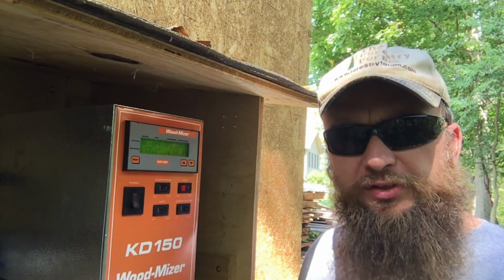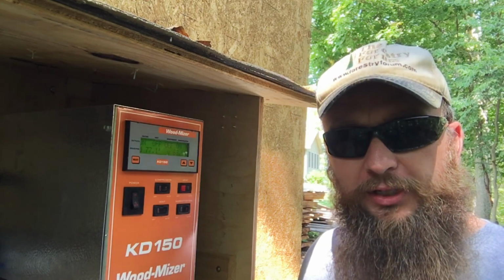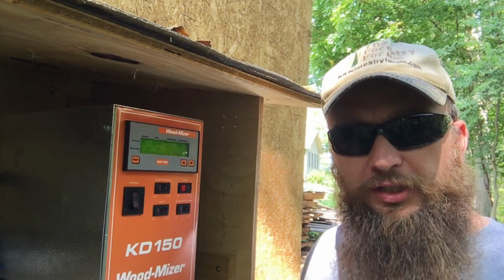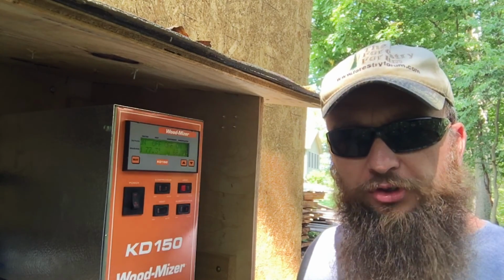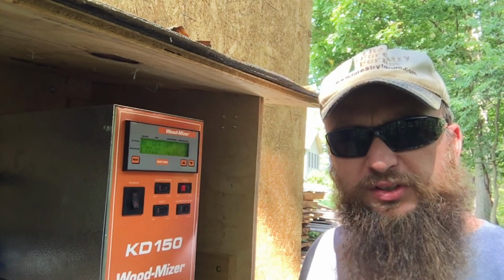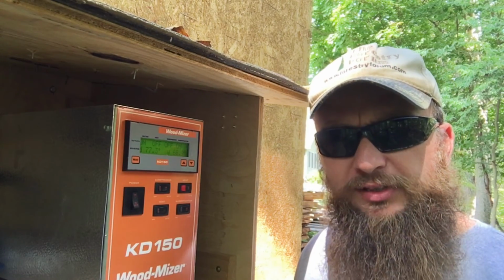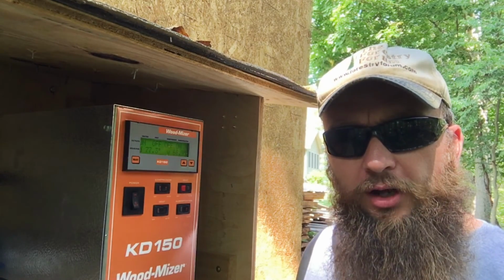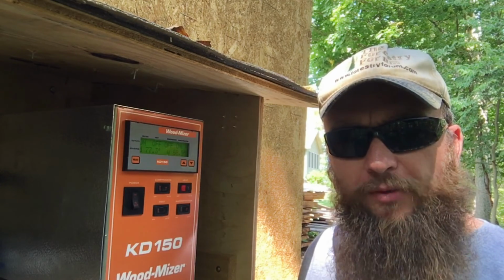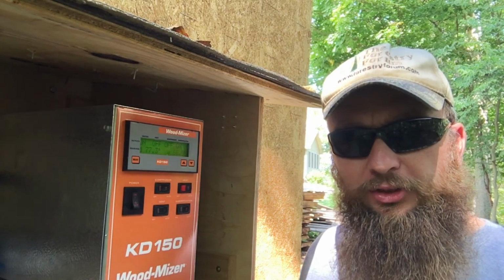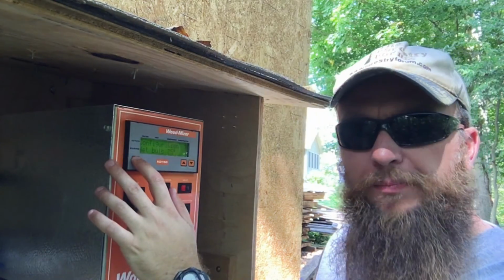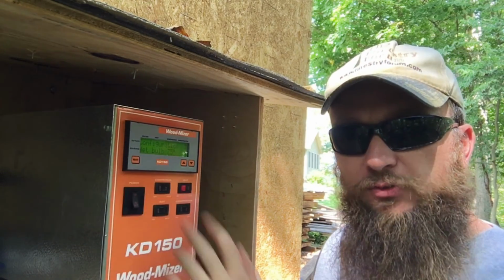And the reason being, once this thing reaches 130 degrees on the dry bulb, which is the overall temperature, the compressor will shut off, and it won't work unless you go inside of the kiln and hit a reset button. So you don't want to go over 130 degrees, or else you have to climb over your lumber stack and try to get to that kiln unit, and that's going to be a bad day. Now our wet bulb is set at 75 degrees, and that's what you want.